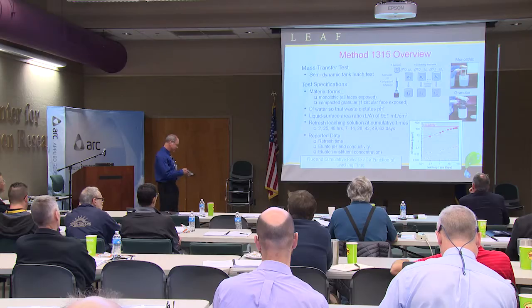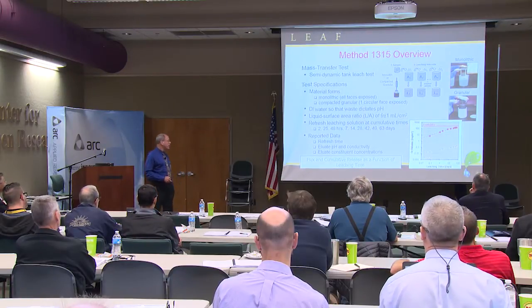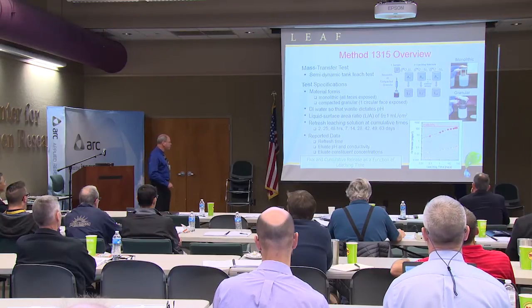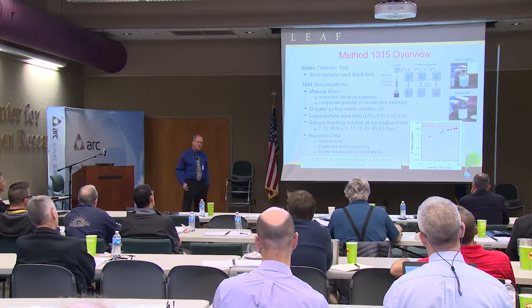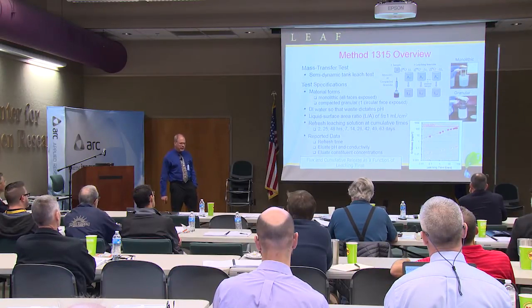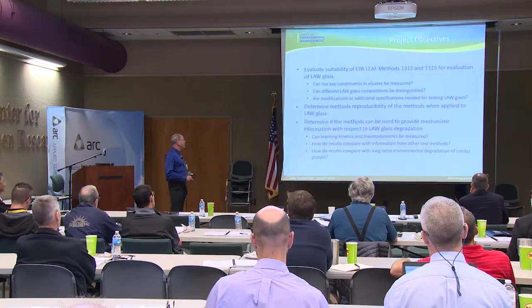DI water is used as the extractant, so the waste or waste form dictates the pH. The liquid to surface area ratio is 9 plus or minus 1 milliliters per centimeter squared, based on the geometric surface area. The leaching solution refresh times go from 2 hours up to 63 days. You'll note that there are uneven intervals. That was originally designed because if you had the traditional t to the 1/2 progression and a saturated solution in each case, it would look like a perfect diffusion case when you hadn't satisfied the boundary conditions. So this gives intrinsic quality control testing on whether or not you're satisfying the boundary conditions. This can in turn be used to estimate a reactive mass transport model for a system, or release as a function of time or mass flux.